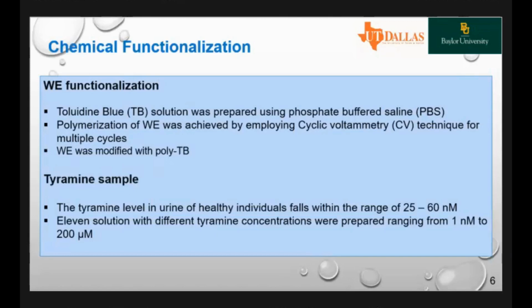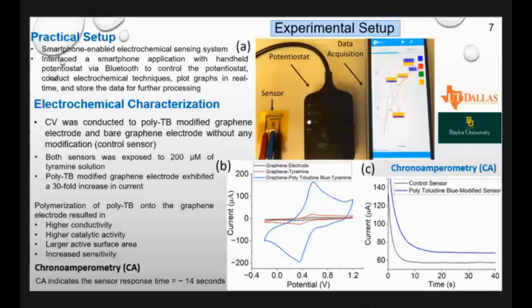The tyramine level in urine of healthy individuals falls within the range of 25 to 60 nanomole. So we prepared 11 different solutions with different tyramine concentrations, all the way from 1 nanomole to very high, a concentration of 200 micromole. So a very wide range of tyramine samples was prepared. And the detection was done with cyclic voltammetry.